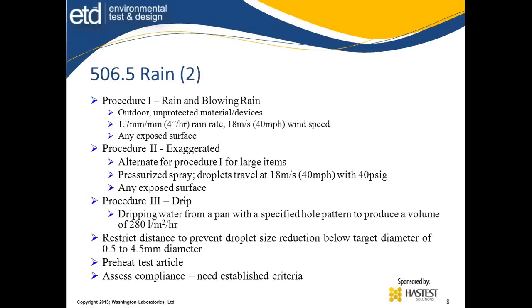Procedure 1 is called out for rain and blowing rain. It's for outdoor unprotected material and devices. It says these 1.7 millimeters per minute or a 4-inch per hour rain rate at a 40-mile-an-hour wind speed, 18 meters per second. And you expose any surface to this wind-blown rain, this blowing thing.